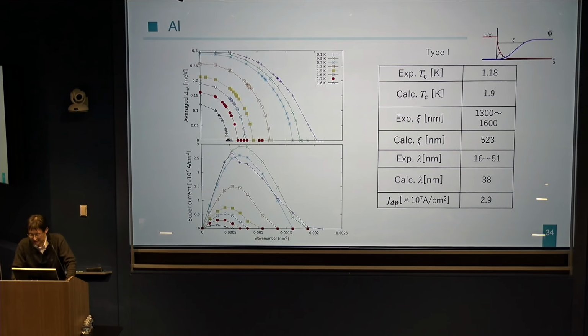In this case, lambda is smaller than 100 nanometers, but Xi is larger than 100 nanometers. So we can safely conclude that aluminum is a type 1 superconductor. And this is also consistent with experiment.